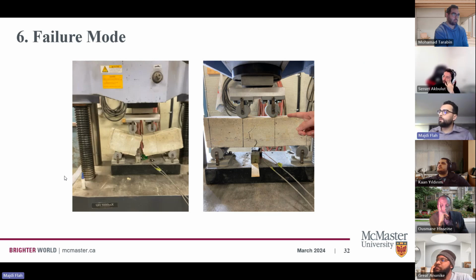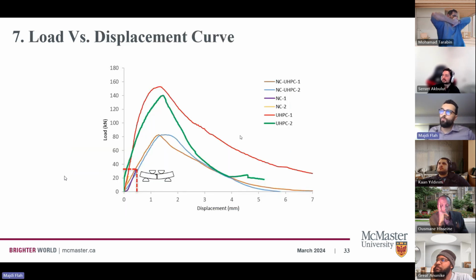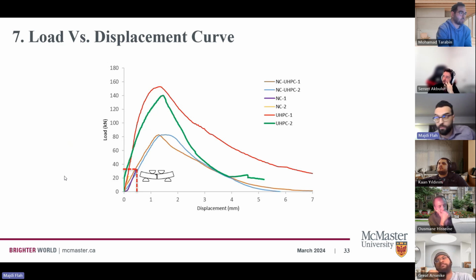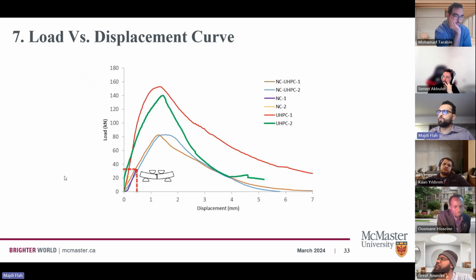And then the crack also went up to the normal strength concrete substrate, leaving a wider gap in there. So if we compare the different load versus displacement curves, we can see that for the normal strength concrete, up to maybe 35 kilonewton, at 0.5 millimeter, we have a brittle failure. However, when we talk about the UHPC, we can go up to barely 150 kilonewton.